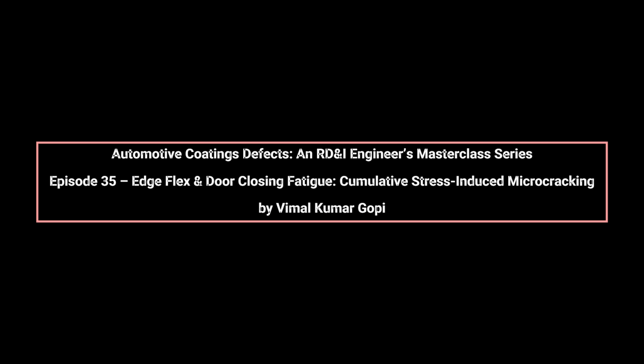Stress relief additives reduce cure shrinkage and lower initial residual stress. Flow and leveling additives help improve edge coverage, reducing extreme thin spots. Flexibilizers increase elongation, but must be used cautiously to avoid compromising mar resistance and gloss retention. No additive can eliminate fatigue failure if geometry and film build are fundamentally unfavorable.